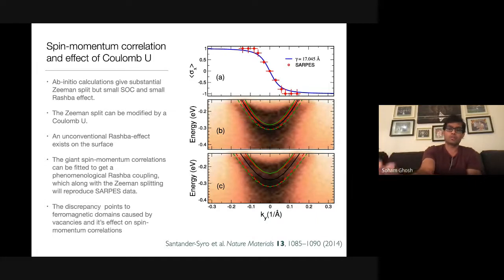So in short, what this picture shows is that you have a metal on top of which you have localized magnetic states, and they're split because of something called a Rashba effect, which I'm pretty sure the speaker after me knows more about than me. So essentially what the Rashba effect does, it locks spin and momentum together. And this picture shows on the right that spin and momentum are indeed locked together.